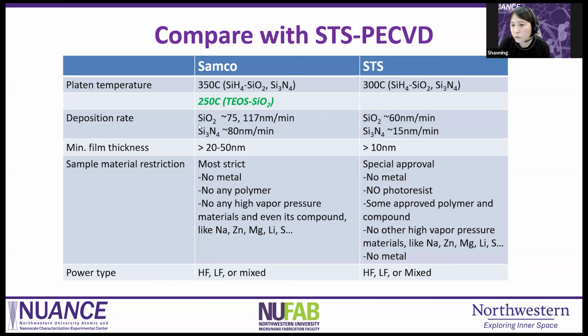Deposition rate. Some of you may like faster because you probably will need a much thicker film, thick in the thin film area, which means over 500 nanometers till 1 micron. That is considered thick film. If you really want to go higher and you want a faster process, SAMCO is faster. You can see the numbers here. 75 is the TEOS deposition rate. 117 is the silane-based oxide rate. But some of you may need to go really thin, down to the 10, 20 nanometer range, which I would suggest the existing STS nitride, which is easier to tune the time.